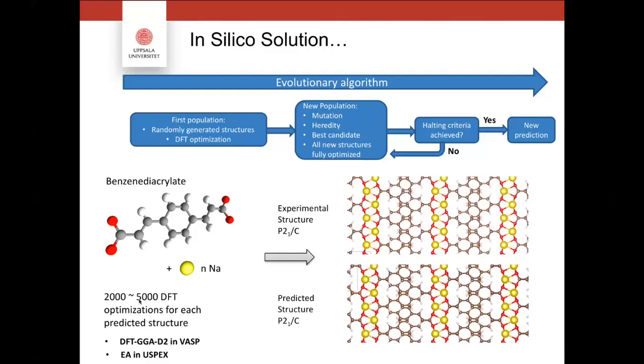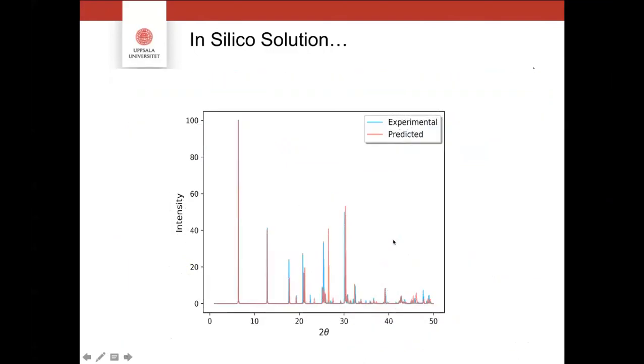So this is our predicted. So you see the experimental structure. This is the predicted structure. We manage to basically predict all different small features of the structure without any experimental input, including the salt layer and the organic part. When we basically compare also the XRD, we can see the excellent agreement between the two structures. So what's the advantage now?